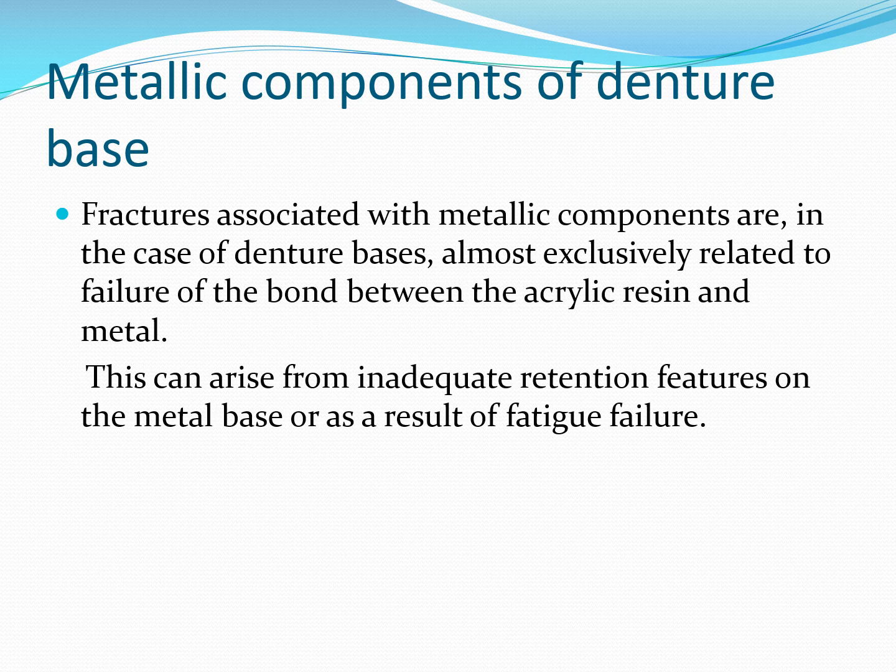Fractures associated with metallic components are, in the case of denture bases, almost exclusively related to failure of bond between acrylic resin and metal.